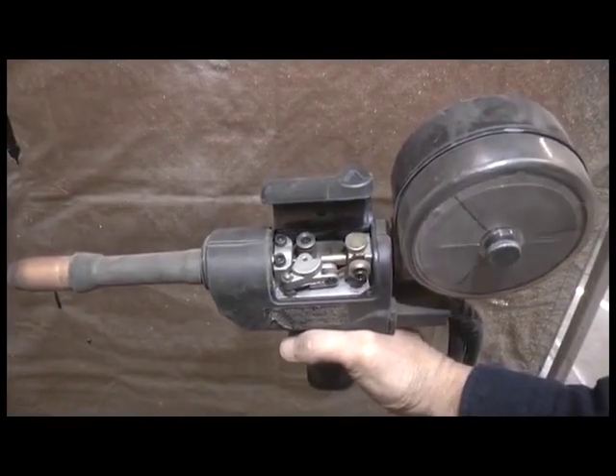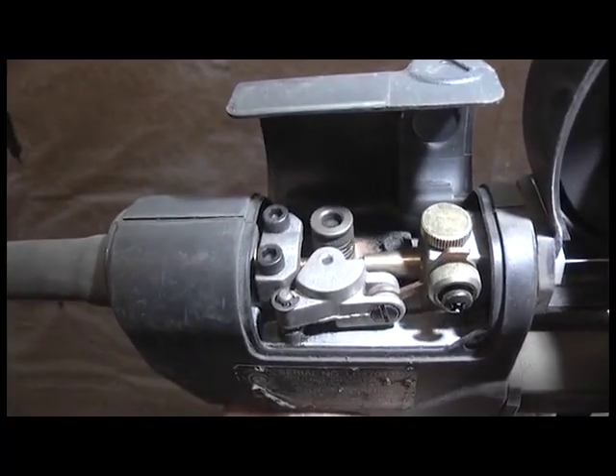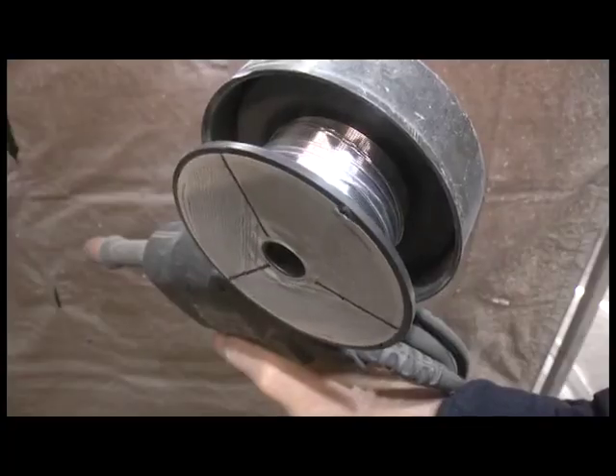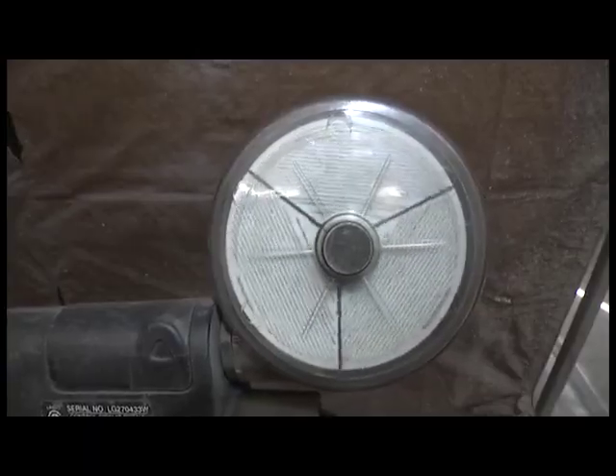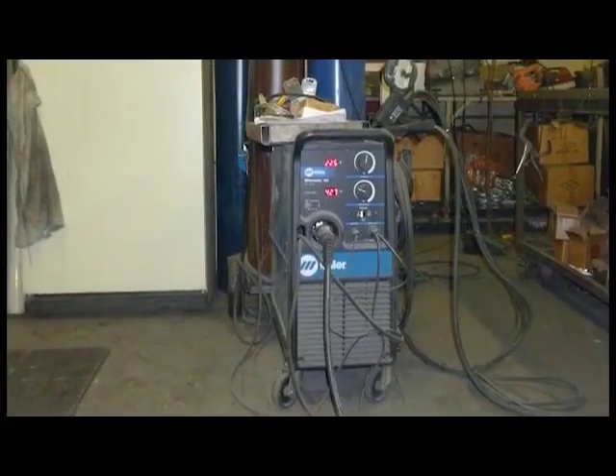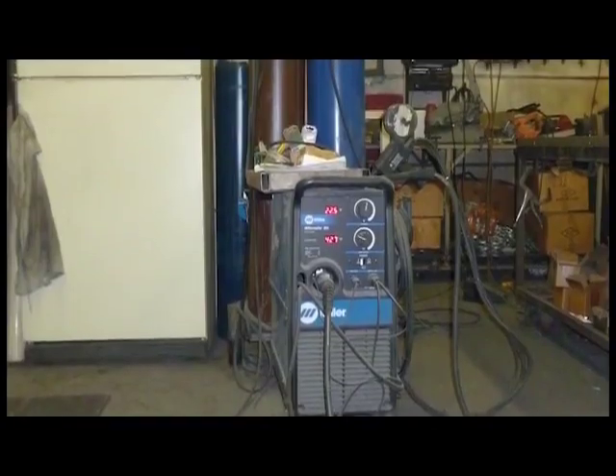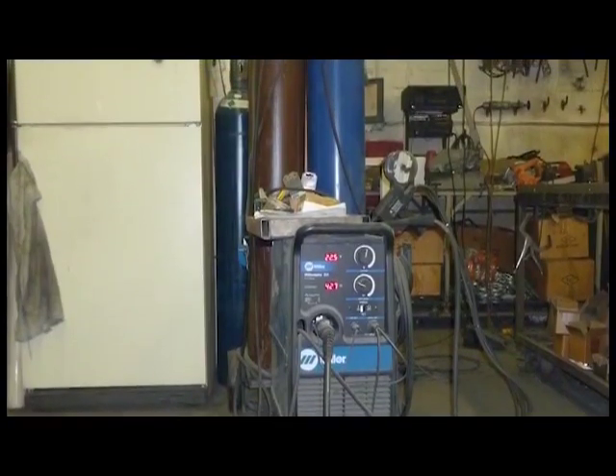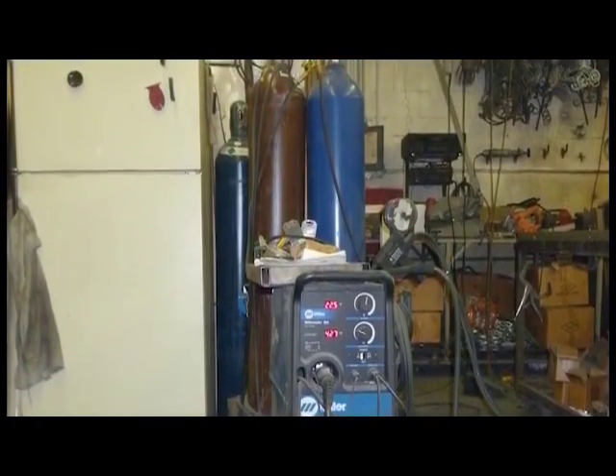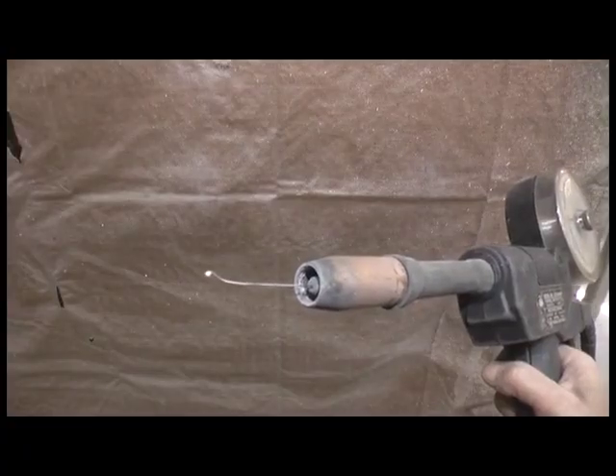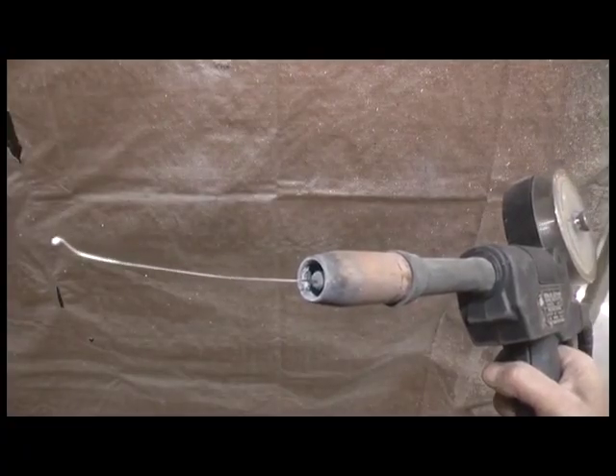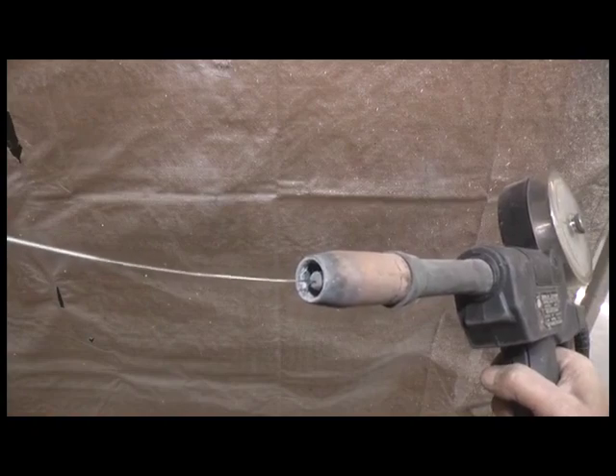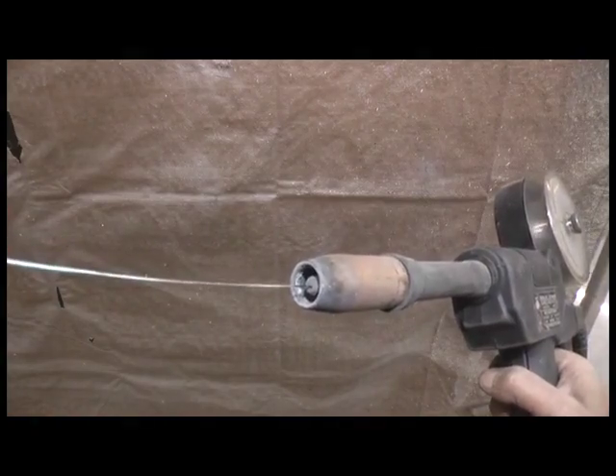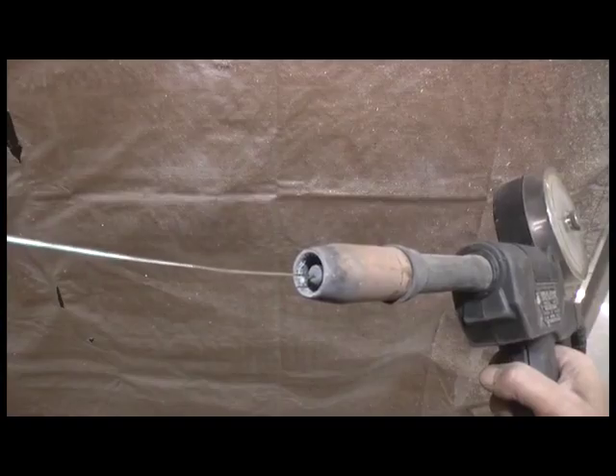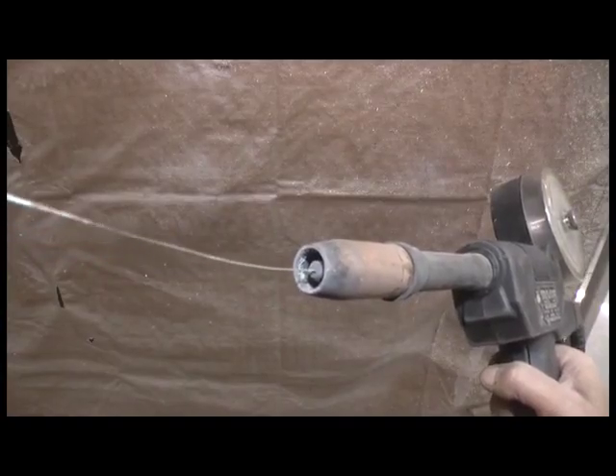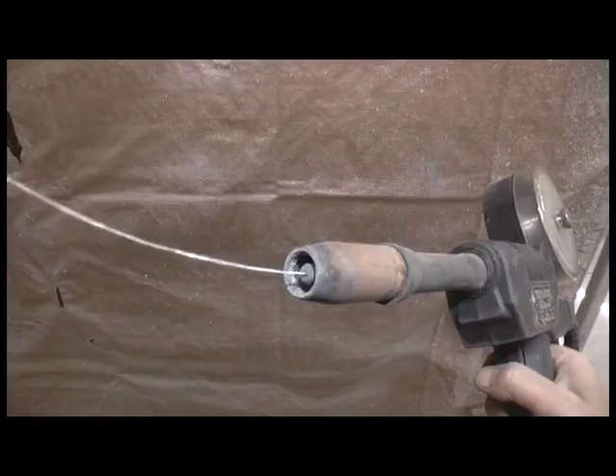When the gun is triggered, rollers powered by a drive motor feed wire from a 2-pound reel mounted on the back of the gun, and the wire is energized by the high amperage power supply. At the same time, a gas solenoid allows the inert argon shielding gas to flow from the nozzles surrounding the wire, shielding the arc and molten metal in the weld puddle from oxygen in the atmosphere.